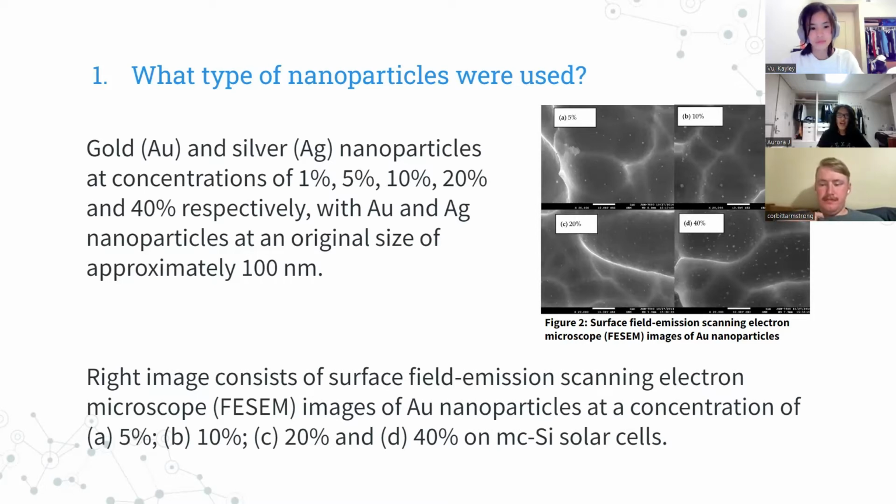It was also found that at higher concentrations, the nanoparticle effect, like the efficiency of the nanoparticles on the solar cells, actually decreased. So the smaller the nanoparticles and the lower the concentration, the more effective they were for the most part. The silver and gold nanoparticles were able to be randomly distributed more often via spin coating, which again broadened the resonance wavelength of the transmittance, which is favored in solar cell applications.